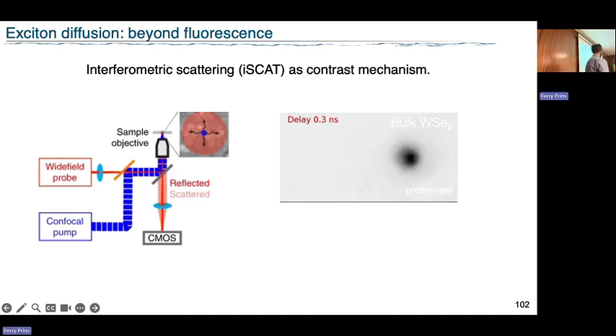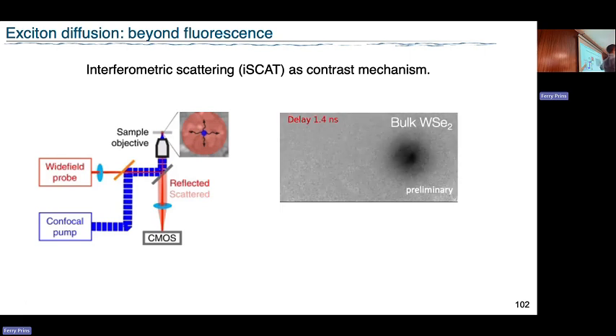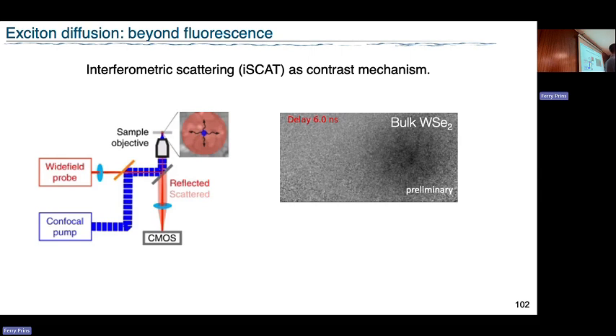Then you see a laser pulse arriving and the carriers inside your bulk tungsten diselenide diffusing outwards, simply because the refractive index is slightly different in the presence of carriers.